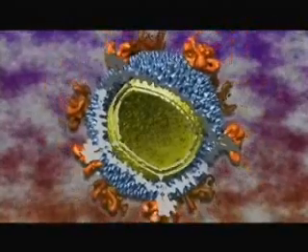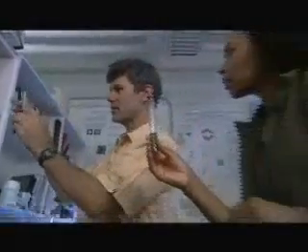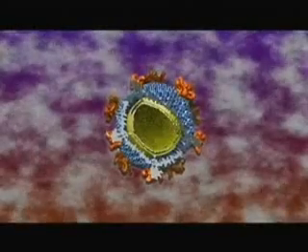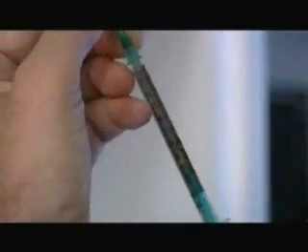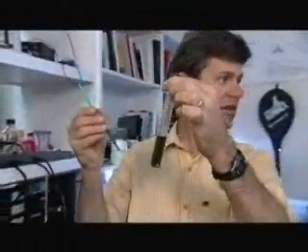It's wrong to think about what we work with as viruses. They start off in Yellowstone as viruses, we get them in the lab, we rip out everything from the inside and it's just a container. We take this container and embed a small metal particle — it's entrapped inside the container like your espresso is entrapped inside the little cup. We get a reaction inside the container: this is a solution of the catalyst, a little cluster of metal ions embedded into the protein cage. As soon as this hits the solution, we're going to get a burst of hydrogen production.